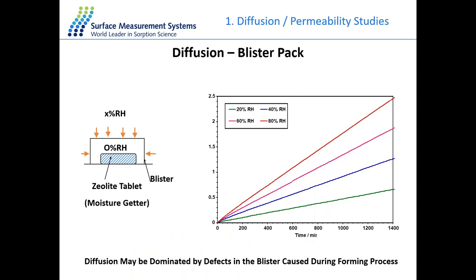So for the zeolite inside option here, we put zeolite inside, it will be 0% RH, and we change the outside concentration to different levels of humidity. In this example it is 20, 40, 60, and 80%. From the slope of this linear line, and also the area of the membranes exposed to the vapor molecule, we can then calculate the permeability parameters of this film sample at different relative humidities.